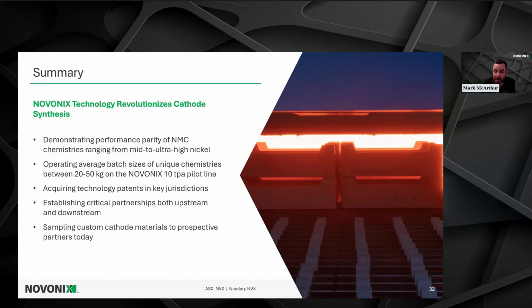And I also mentioned that we have our pilot prototyping facility here. On average, we're generating 20 to 50 kilos of product on our 10-ton per year pilot line pretty regularly. Some of our largest batches are 100 to 120 kilos. Really, the sky is the limit for us when it comes to the utilization factor of our equipment. And I do want to mention that the photograph on the right-hand side of the slide is actually a real picture from our RHK, our roller hearth kiln, with a set of 4 saggers or crucibles going into the hot zone.